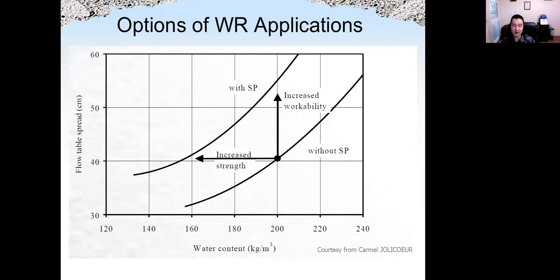Like we can see from here, the options for water reducing applications. The X axis is the water content, the Y axis is the slump flow. So we keep the water content constant. When we add superplasticizer, the workability will be higher. But if we keep the slump constant, like in these arrows, we can reduce the amount of water. So we use a lower water cement ratio, and the strength will be higher. We can also use less cement.